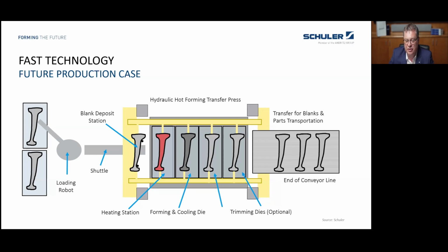Of course, this is a different story because the cycle time of this transfer press will be somewhere between 10 and 16 seconds, depending on the size of the part and the thickness of the material. And a traditional trimming line for such parts normally runs much faster, more or less double the speed. So it's questionable if the trimming should be added there, but it's a matter of calculation. You can also take them out and trim them on a separate line. Other than this, it is a traditional setup of a transfer press with a destacker.